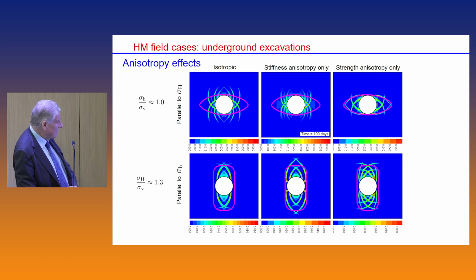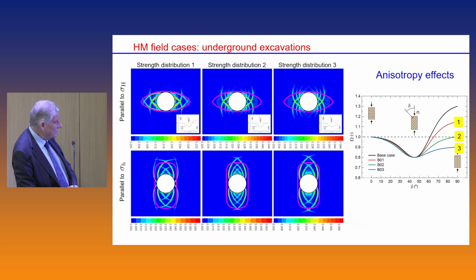rather than the stiffness anisotropy of the material. We can also check the different distributions of strength, different types of anisotropy, what results do you have? Again, when I'm parallel to the major principal stresses, if I use number 1, which is similar to the one I was showing before, you get the right result, but not so much when you use other distributions, which is a kind of evidence pointing towards a certain type of distribution of strength. Again, when we go to the non-isotropic stress state, this stress state dominates, so for the three ones you still get quite a large vertical development of the EDZ, similar to observations.